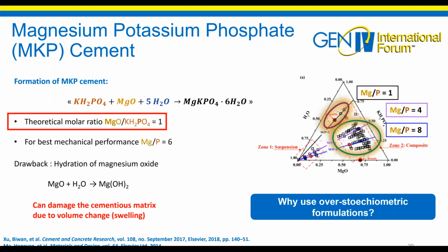The chemical reaction for the formation of the phosphate matrix is as follows. The acid, which is potassium dihydrogen phosphate, reacts in the presence of water with magnesium oxide to form struvite-K. This reaction is characterized by a molar ratio of magnesium to phosphate equal to 1, but the literature says that using a higher ratio, about 6, allows high mechanical performance.